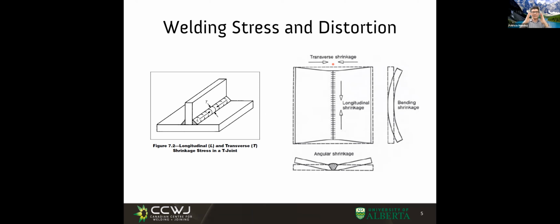The bridge has these two curved beams, and then it has these cross members. And they were afraid that when they would weld the cross members, they would shrink with transverse shrinkage and bend all these other members that were carrying the load. That was a big deal. And they did lots of tests for that. And in the end, it was not a problem.